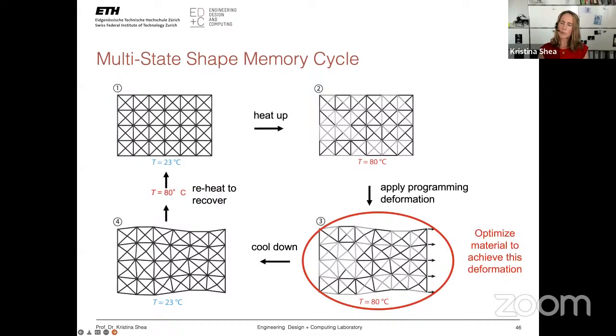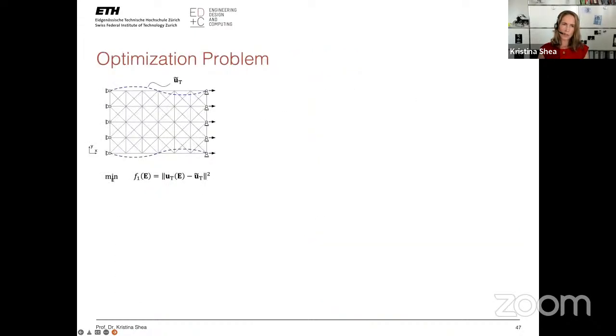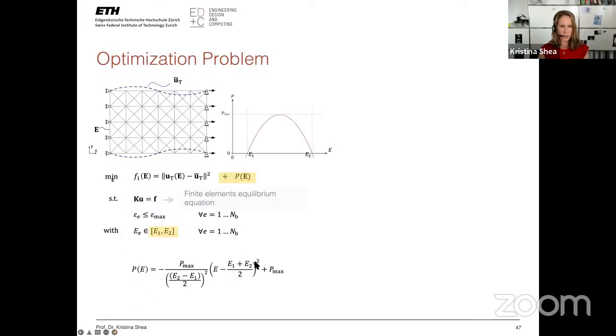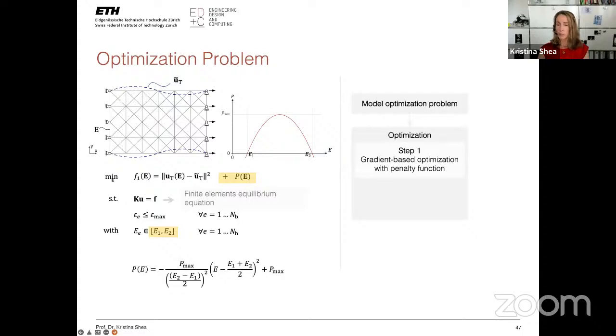And so it became an optimization problem to optimize the material distribution to achieve this deformation. The optimization problem is then we have a lattice structure. We're going to optimize for a given deformation U, subject to the normal finite element equilibrium equations. These are just considered simple truss bar members. What we want is to use these two materials and distribute them in the structure. So he uses a penalty function to do this. He creates an optimization model in the initial case that's using gradient-based optimization with the penalty function to create the initial distribution.